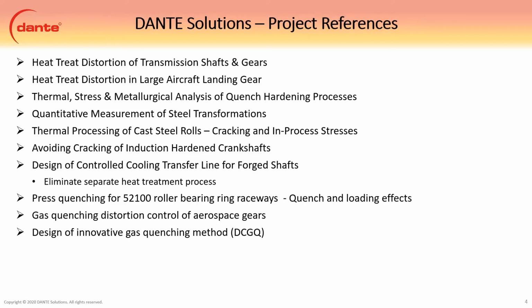All right, so some quick project references. We do a lot of transmission shafts and gears, and a lot with the aerospace industry because their tolerances are so tight. We've done obviously thermal stress and metallurgical analysis of quench hardening, and that's liquid quenching, gas quenching, even salt bath quenching. We've looked at quantitative measurements of steel transformations using dilatometry, cast rolls in the steel producing sector. A lot of induction models lately. We don't model the actual electromagnetics, though we can predict the stresses and strains from the process itself, but I'll get into that with some examples later on.